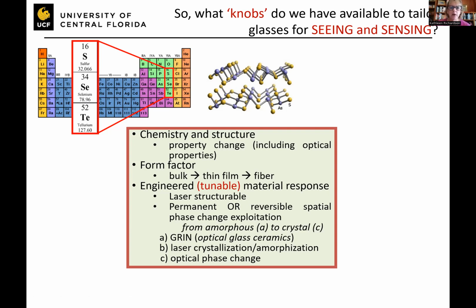So because these are big anions and cations that participate in these structures, their bonds are typically much weaker than that found for metal oxygen bonds in oxide glasses. As a result, these materials typically have much lower Tgs and much steeper viscosity temperature curves. The other thing that we can use as a knob with these,